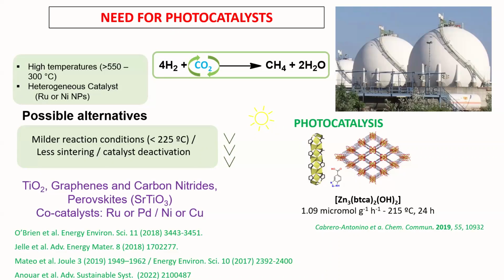And obviously when these reaction conditions were altered, there were problems like sintering and catalytic deactivation. These are some of the catalysts which have been reported for these reactions, like TiO2, graphenes, carbon nitrides, and perovskites, which are well-known materials. The co-catalysts typically employed for these reactions are ruthenium, palladium, nickel or copper.